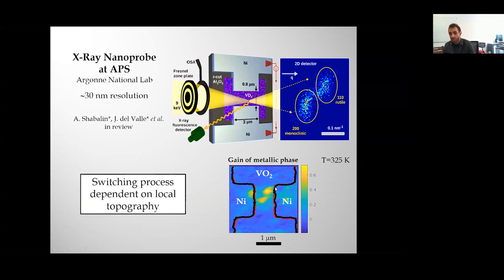So what this is showing is that the switching process is actually extremely dependent on the particular local topography of your device. So you might have two devices that look completely the same, but just because the grain arrangement might be a little bit different, that is expected to have a very strong influence on how the switching will take place in your device. And that explains the big variability.